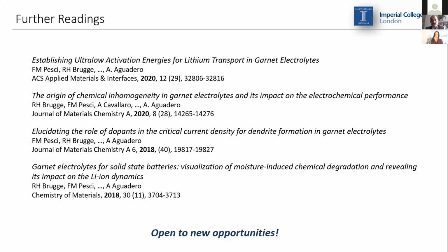So another question: did you consider measuring the residual stress of garnet electrolyte after sol-gel powder formation? With etching, some of the residual stress may be released, and with thermally coupled etching, the electrolyte would be more stress-free and attain stability, therefore have lower resistance during EIS. Did you observe any change in average grain size of garnet before and after thermal treatment?